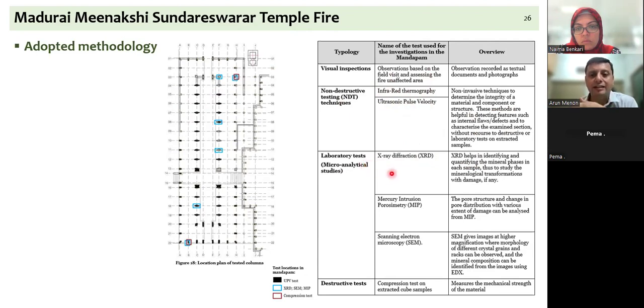Laboratory tests on extracted materials, microanalytical tests were conducted, such as X-ray diffraction studies on the material, porosimetry using mercury intrusion porosimetry. We did scanning electron microscope imagery on the stones. And then we also extracted some stone cubes from columns which were damaged at different levels, and did compression testing on these extracted samples as well.